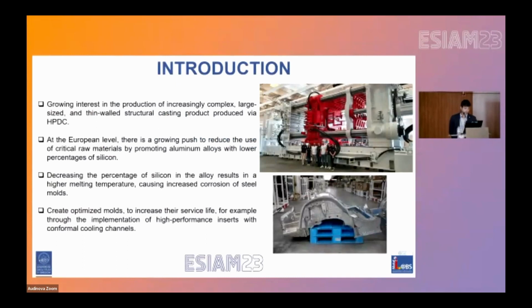Aluminium, silicon, and magnesium is one of the most industrialized alloys for this kind of application. However, at the European level, there is a growing push to reduce the use of critical raw materials by promoting aluminum alloys with a lower percentage of silicon. One such alloy is the aluminum silicon 7 magnesium, typically used in gravity casting. However, decreasing the percentage of silicon in the alloy results in a higher melting temperature that causes an increase in corrosion of the steel mold.